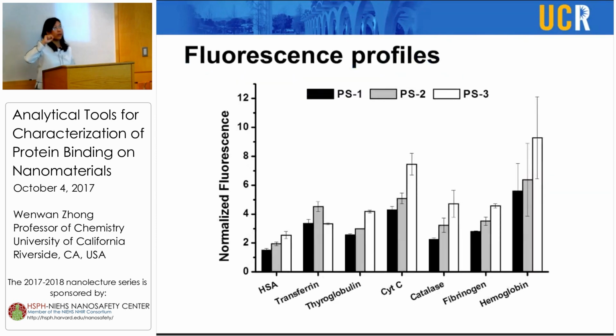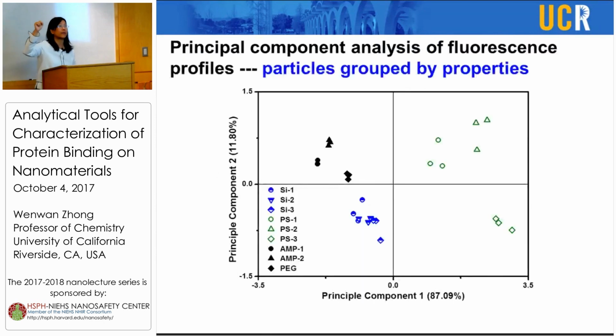And this is the fluorescence profile we obtained for the 3 polystyrene particles that we tested and around all these 7 proteins. But we see the majority actually showing an increase in fluorescence, which indicates a certain kind of conformational change and opens up more lysines to be labeled.